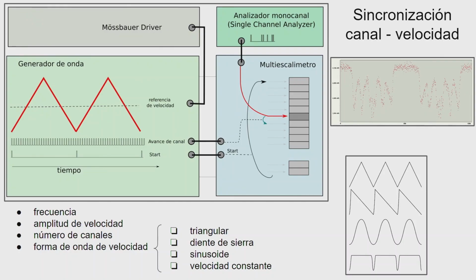But then you can fold this spectrum. You have to be very careful what is the folding channel that you are going to use, to get just a single spectrum. And it's not very clearly seen here, but because of this motion of the source, there are parts of the cycle of motion where the source is closer to the detector, very little, of course, and parts where it is farther away from the detector. So you end up having something like a background, which increases here and decreases here. You understand? The folding procedure is a way to get rid of this effect, at least to the first order.